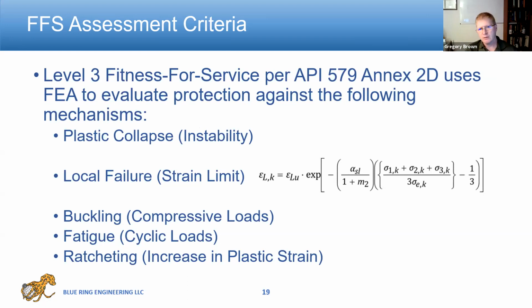So the way the rules work would be, since this is a physical case where the structure goes unstable, if you build an appropriate computer model, a physical instability should cause an instability in your computer model. So we can use a computer model to determine if a structure is stable. Then we put on additional factors of safety. You also have to evaluate what's called local failure. This is making sure you don't get too much plastic strain, permanent deformation at locations on the tank. And that just has to be less than a limit.